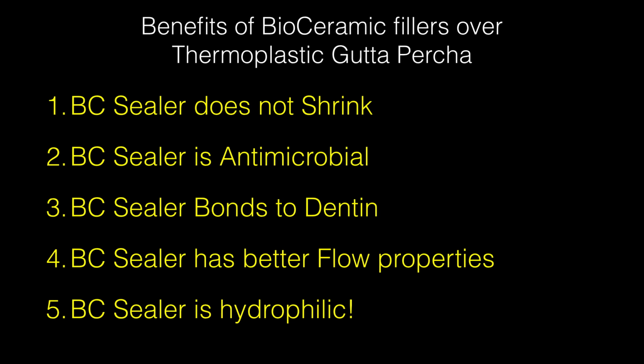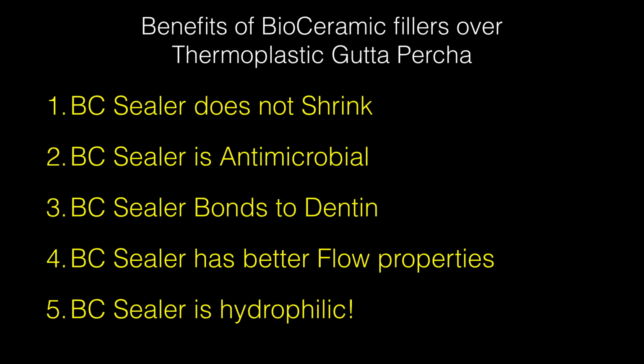But what are really the benefits of bioceramic sealer over thermoplastic gutta-percha? Well, first and foremost, bioceramic sealer doesn't shrink, whereas thermoplastic gutta-percha shrinks anywhere from 2 to 7%. You have bioceramic sealer, which is antimicrobial, whereas gutta-percha is not antimicrobial, it's just inert. You have a bioceramic sealer that bonds to the dentin, but thermoplastic gutta-percha doesn't bond. In fact, when it shrinks, it pulls away from the dentin, and that's the problem.